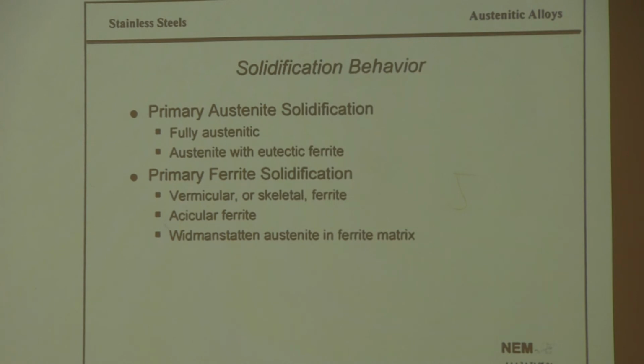And so there's something called austenite solidification, or A-type solidification. You can get fully austenitic if you're far enough over on the phase diagram. If you're a little bit closer to the boundary, you'll still end up with a little bit of ferrite, and that's called AF solidification. Or you can solidify as ferrite, which then will transform partially back to austenite as it cools, and that's called FA solidification.